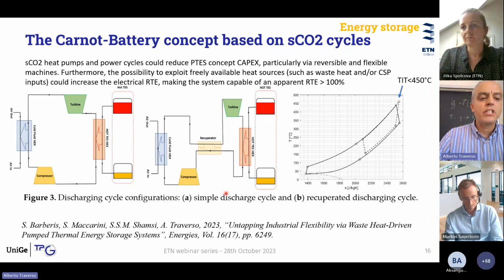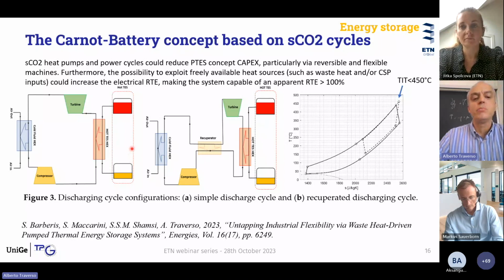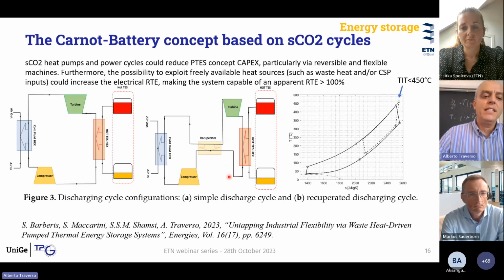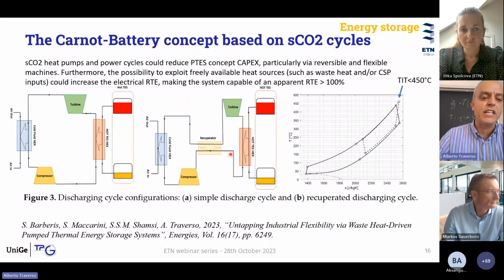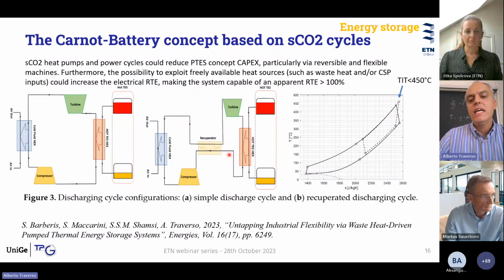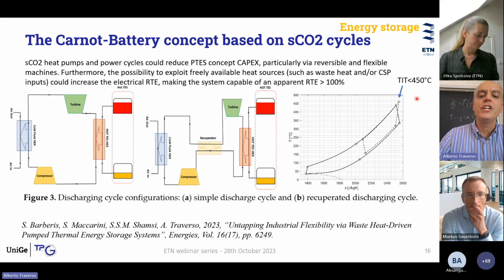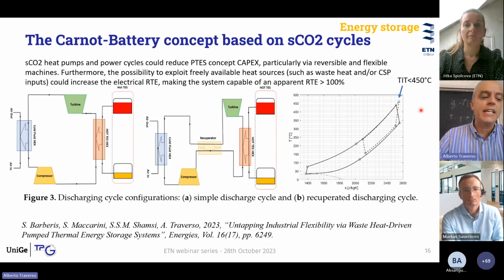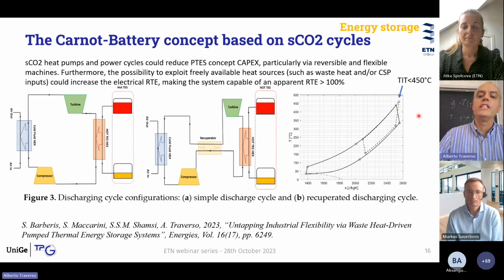If we look at the layouts reported here, for instance, we are showing two different layouts for the discharge phase, where on the left is a simple supercritical cycle, and on the right we have a simple recuperative supercritical cycle. In this case, the charging and discharging cycles interact in order to define the specification of turbomachinery, in particular if reversible turbomachinery is to be developed. But if we look at the TS diagram of the two cycles, one charging phase, the other discharging phase, and we look especially at the expander inlet condition, we see that even for the Carnot battery, we are talking about inlet conditions which are similar to the waste heat recovery case. The optimal TIT case is a little bit higher, 450 degrees C, during the charging phase, but they are quite similar to that case.